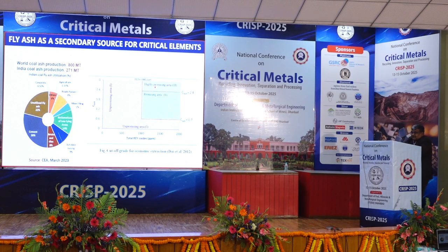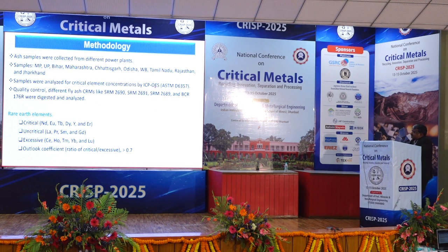So those are the two yardsticks we are using to characterize the Indian fly ash. Coming to methodology, we collected ash from different power plants across the country, and we did elemental analysis following the ASTM protocol. For data quality control, we used different certified reference materials, including rare earth ores, and we are getting very good recovery for lithium metaborate-based digestion, even with an ICP-OES.